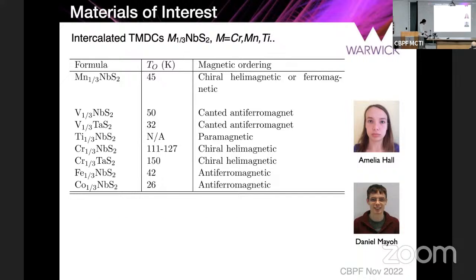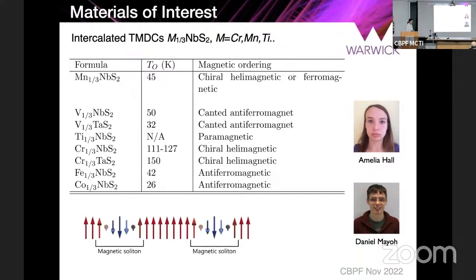And why are these interesting? Now, it's interesting to us because some of these exhibit what's called a magnetic soliton. So what's a magnetic soliton? A magnetic soliton is just regions of ferromagnetism which are separated by a 360 degree domain wall, by this helical arrangement of the spins. These have been seen in chromium niobium sulfide and chromium tantalum sulfide, and these are seen as being very related to our skyrmion structures.